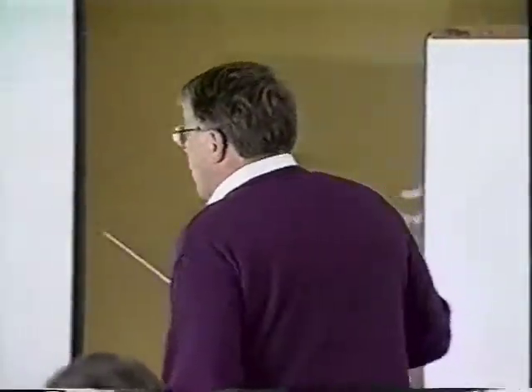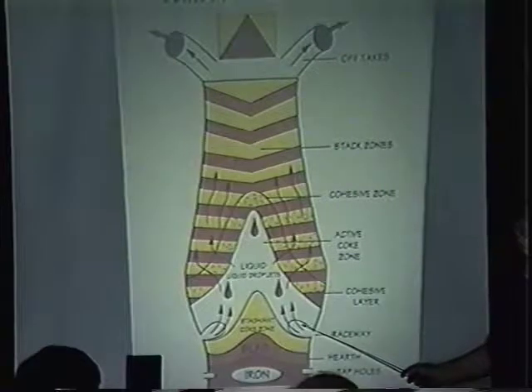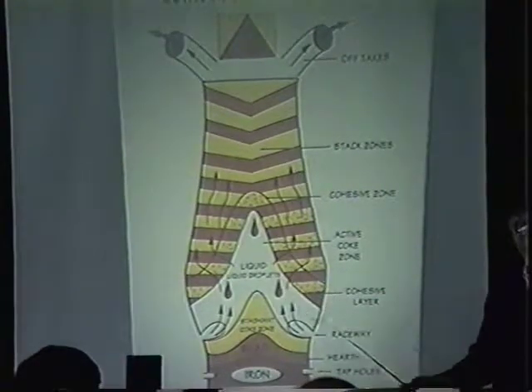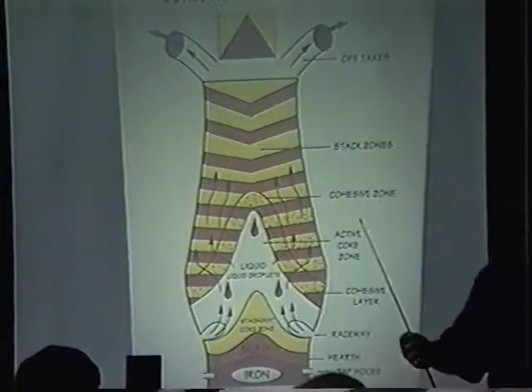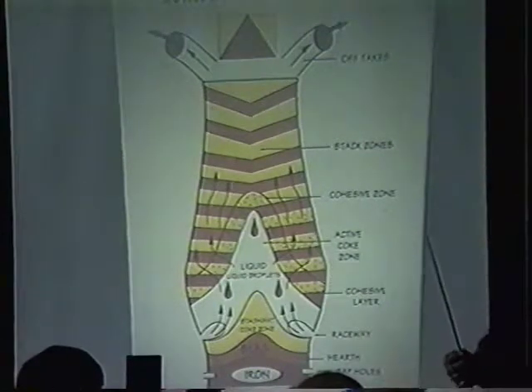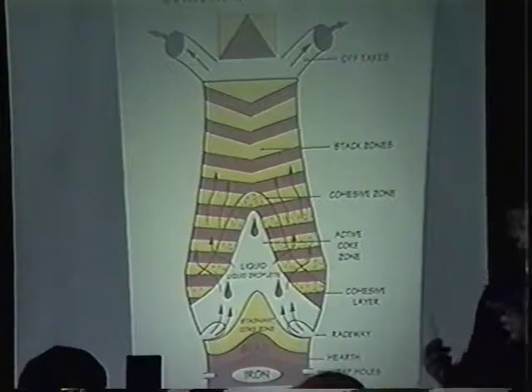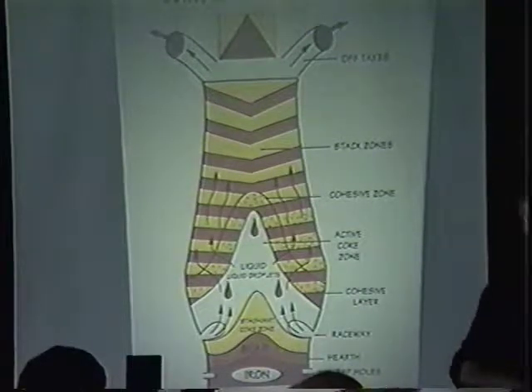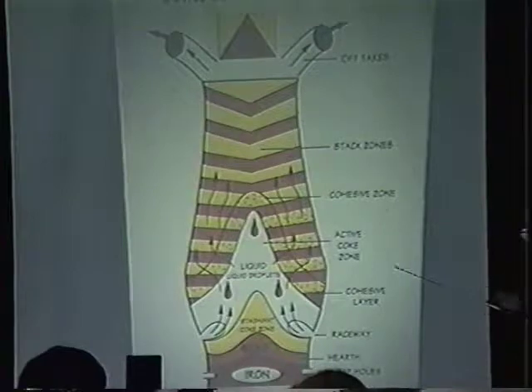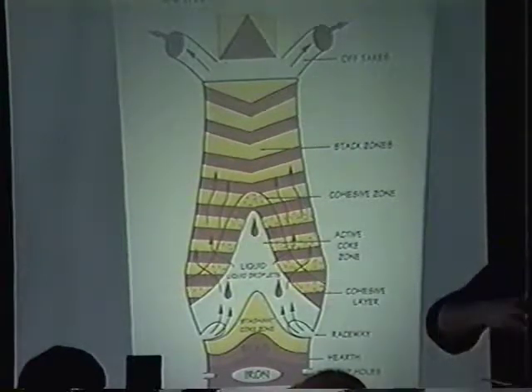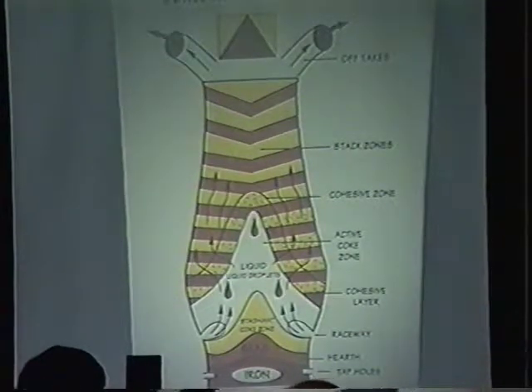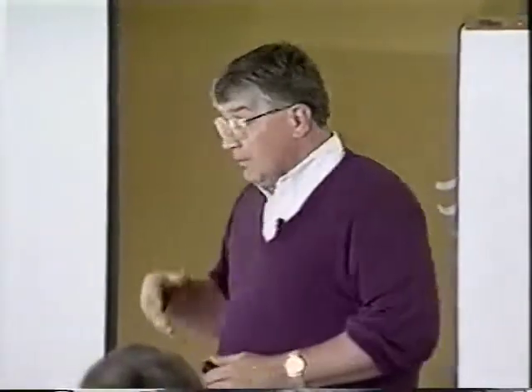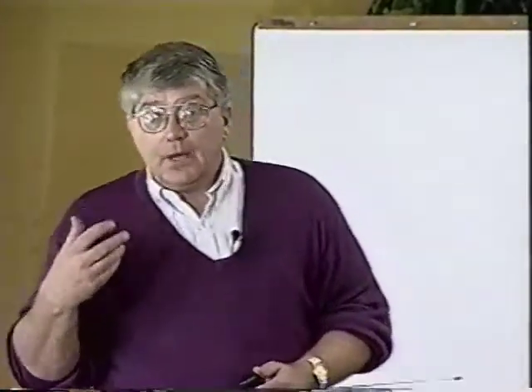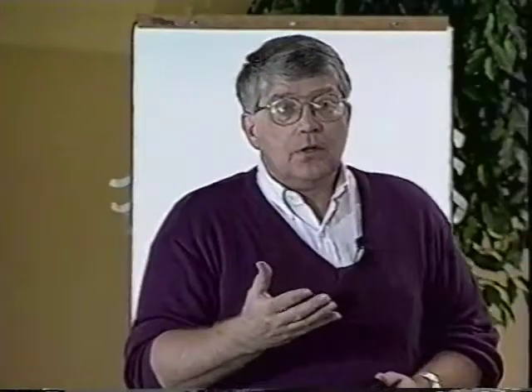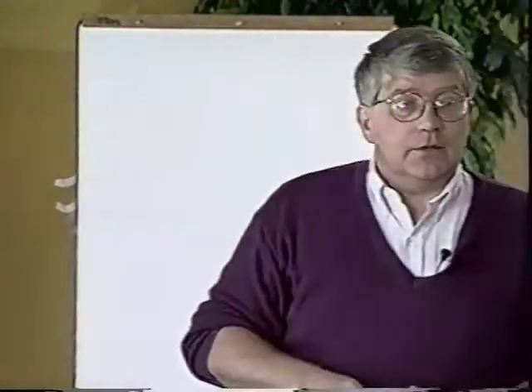The other thing about coal is injected at the tuyeres. And what is coal? Coal's carbon with volatile matter in it. But we use a low vol coal in our injection, so we only have about 21% volatile matter. And when you're talking the temperatures we're talking here, you're going to volatilize and burn off all that volatile matter in there. So, it replaces coke about pound for pound. You inject a pound of coal, that's less than a pound of coke you need to add to the furnace.